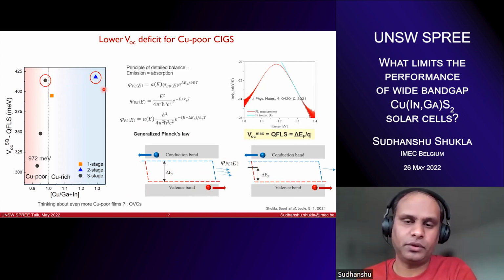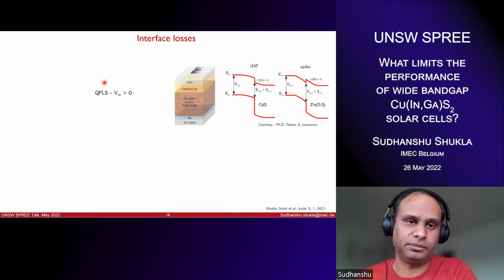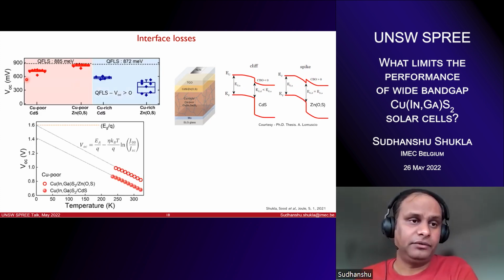So we wanted to see what is the difference in terms of interface recombination. As you can see, you should have a spike-type configuration in order to have less interface recombination. So you would not want to have cadmium sulfide, but rather something with a high conduction band, zinc oxysulfide. So we did that.